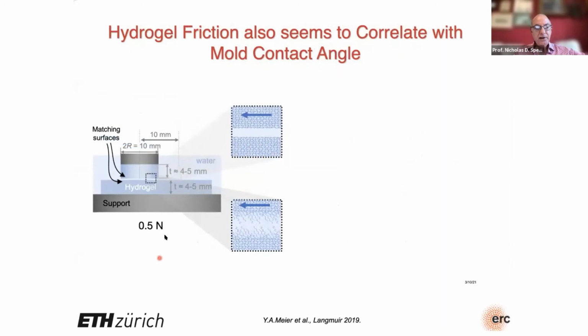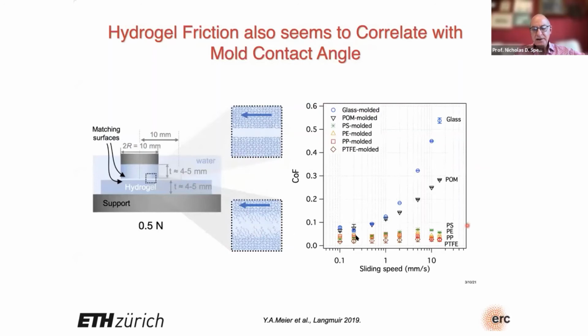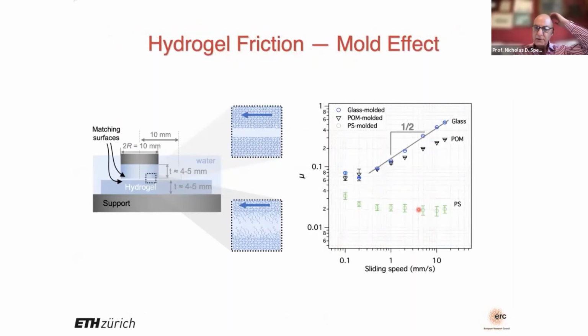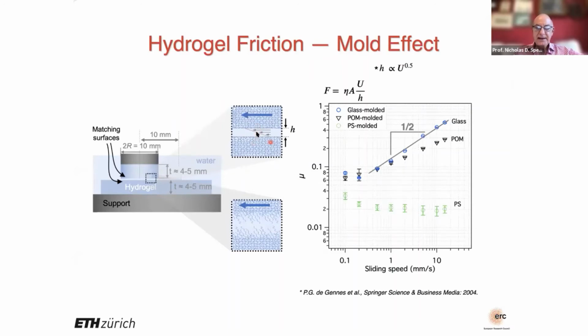Now, the friction we're measuring here on a macroscopic scale, the frictional differences are also great. And we notice something interesting in the case of hydrophobic systems. So POM is somewhere in the middle, but in the case of hydrophobic systems, we don't see any speed dependence of the friction coefficient, whereas in the case of glass, we see a strong speed dependence. And if you look into it, it seems to go as the square root of sliding speed. And there are reasons we can explain for this due to the hydrodynamics of the system. We would expect that for something that has more or less solid surfaces, this separation would go with speed more or less to the square root.